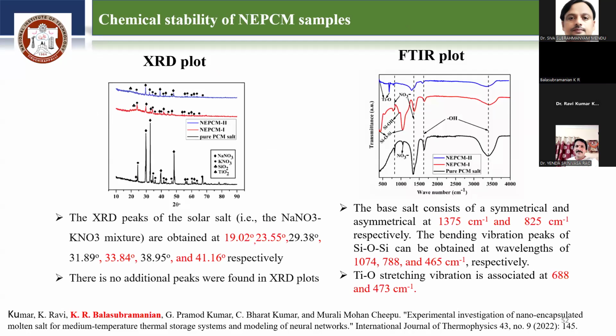Then the next thing is that we need to determine the chemical stability of the samples. So XRD analysis is done, and Fourier transform infrared analysis is done. From the XRD peaks of the solar salt NaNO3 KNO3 mixture, we can see the black one is for pure PCM salt, the red color is for NePCM, and the blue one is for NePCM 2. Almost it matches. There are no additional peaks in the XRD plot.